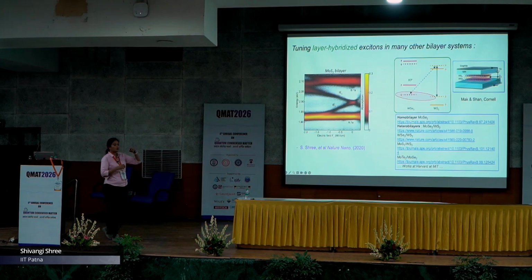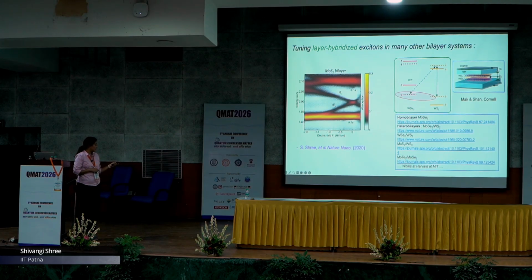field. So, both are like the electron sitting in the top layer and the hole in the bottom layer, which are hybridized, and then you have the electron sitting in the bottom layer and the hole hybridized again in the 2 layers. So, these are 2 degenerate states at 0 electric field, but when you apply some electric field you will see the splitting. Okay. So, this is what we see here, and as this interlayer exciton has some mixing with the B state, we also see some anti-crossing and very strong coupling between the 2 states here at higher fields.